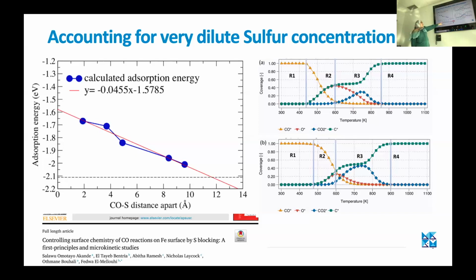So we started to look at CO co-adsorption, but if you remember, I told you that the H2S barrier was really small, 0.1 electron volt. So we assumed that sulfur will be dissociated on the surface, okay? Sulfur will be on the surface, and then hydrogen would have desorbed in the molecular phase. So every CO that comes on the surface and lands would feel the presence of sulfur.